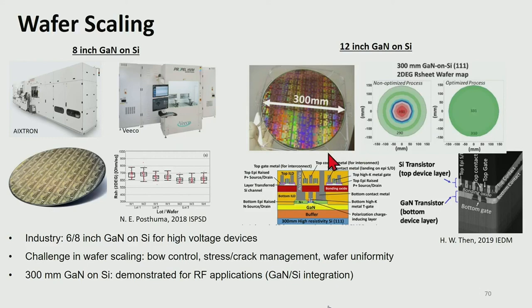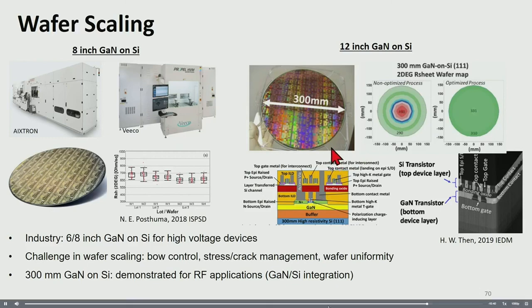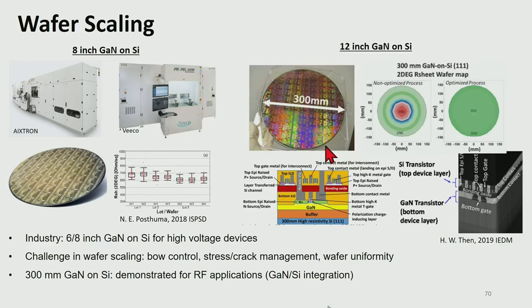Lastly, there has been continuous effort to scale up the gallium nitride wafers. In the current GaN industry, either 6-inch or 8-inch GaN wafers are used. But about 2 years ago, in this conference, 12-inch GaN on silicon technology was published. Although used mainly for the RF applications, which require a relatively thin buffer, the excellent 2DEG uniformity across the 12-inch wafer shows the potential of the gallium nitride wafer scaling.